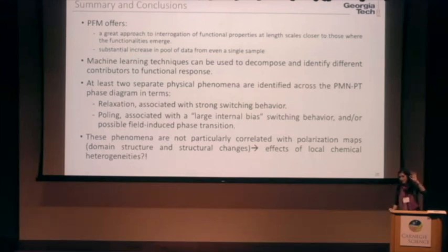There might be specific locations, but percentage-wise, there is maybe 5 to 10% correlation with the polarization, where you would have to have a very high density of polarization change, or basically it could be related to structural changes in the sample, versus locations in which we do not have any correlation. In fact, you would have a very uniform polarization both in and out of plane, and then suddenly you do see very different behavior, which to us means it doesn't seem to be correlated with the direction of the pre-existing polarization. It could be more correlated with something else that we cannot see with PFM, chemistry we cannot see with PFM.